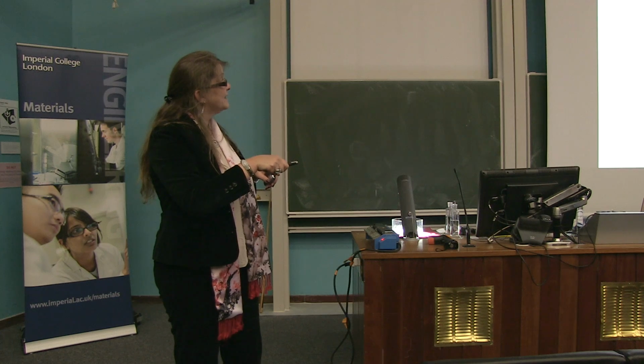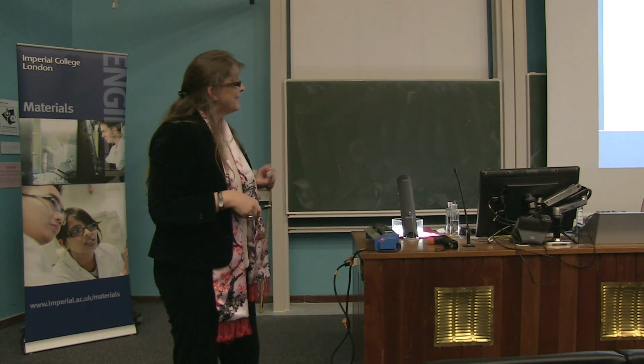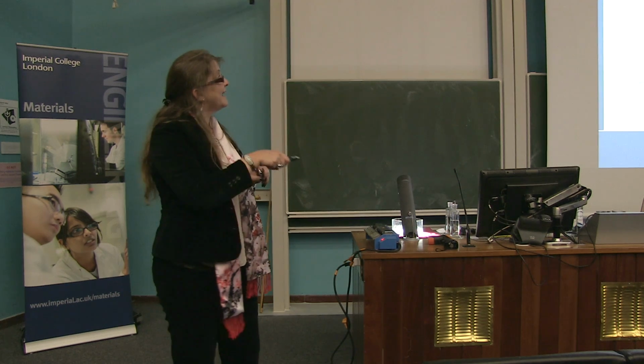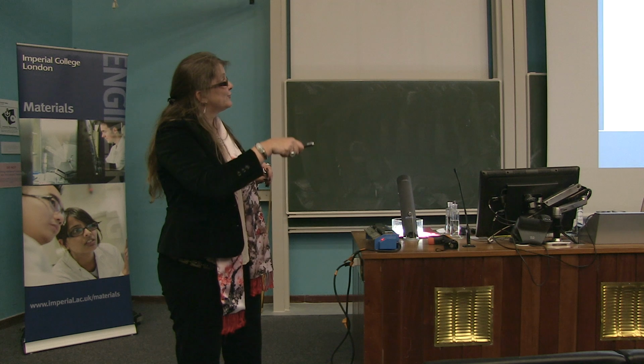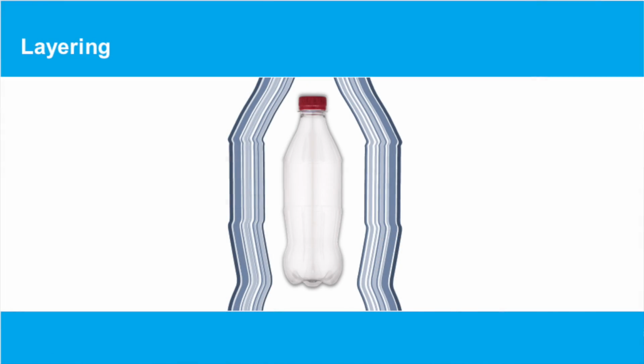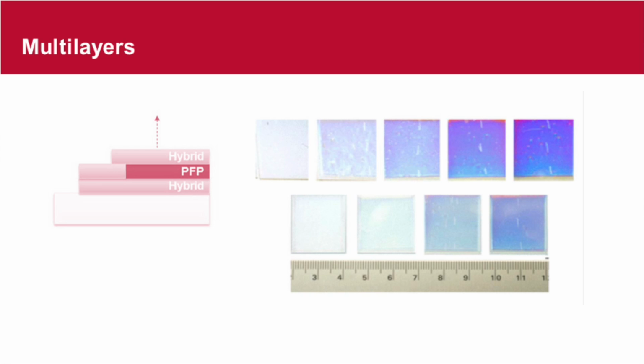And the simplest is to stack them. So it's very similar, and I hope this animation works, like in a PET bottle, where we stack multi-layers, some to keep air out, some to keep the liquid in, some to give it toughness. So very similar, we now just stack different materials to get different functions. And you see here, so we have a high refractive index material, looks like this. Then we add a low refractive index material. This is also a plastic, it's similar to Teflon actually. Then you get this, and then you go 3 layers, 4 layers, 6 layers, whatever.